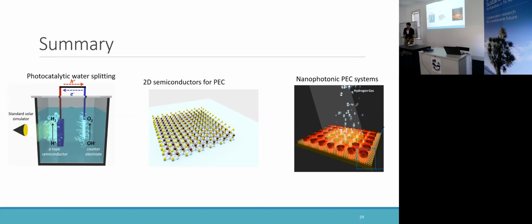So any questions? Given that you're effectively, if you use high laser power, melting your nanoparticle of gold, does that mean that you get some exchange of gold into your 2D semiconductor? Is there any mixing with that 2D? No, for this 2D semiconductor, in this case, we don't use a laser to shine on it, and also we don't use a high power laser, just normal white light. So you're not hot enough. No. Okay.